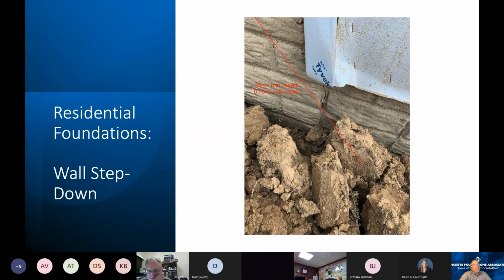But in this particular case, we've got a vertical crack right underneath where it says Tyvek. Now this happens to be a step down. On the left-hand side, the wall's higher. On the right-hand side, underneath the window, or underneath the framing, it steps down, and so the grade is stepping down, moving from the left to the right. In talking to the contractor, they had no reentrant corner trim bars, nothing to prevent crack development.